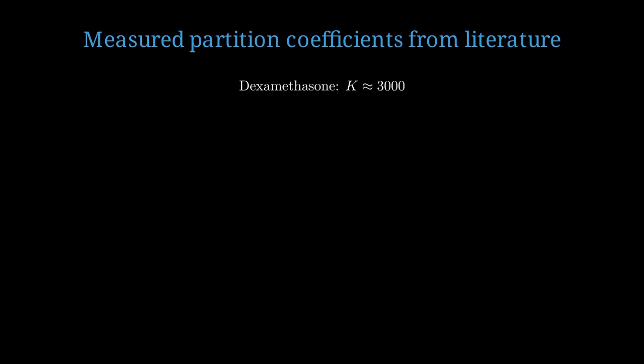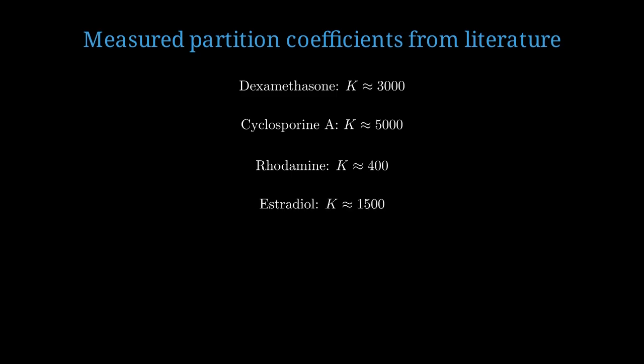Dexamethasone has a partition coefficient of approximately 3000. Cyclosporin A is even worse at about 5000. Even fluorescent dyes like rhodamine are affected, with K around 400. Estradiol, an important hormone, has K around 1500. These are not small effects. These are massive systematic errors that invalidate quantitative conclusions.